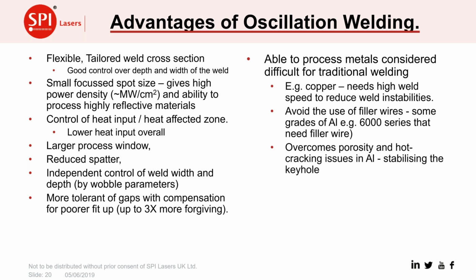What we're also able to do is process many materials which are difficult or considered very difficult to weld with standard processing, where we might have a very narrow process window, but now we can use oscillation welding to give us a reasonably good weld and find it quite easily. So we can do copper, and we'll see some examples of that, at a high speed. The small focus spot size gives us a chance to reduce the weld instabilities. We can do these welds without the need of filler wires, although some aluminium grades still benefit from that. And we can overcome a lot of porosity issues in welding aluminium because we are able to stabilize the keyhole because of the high power density.